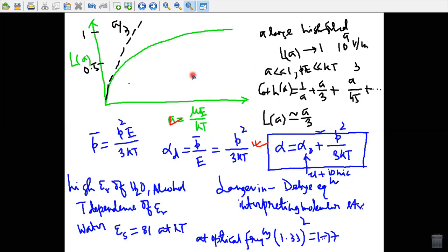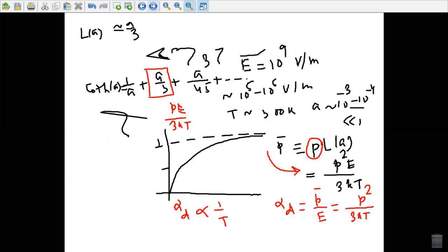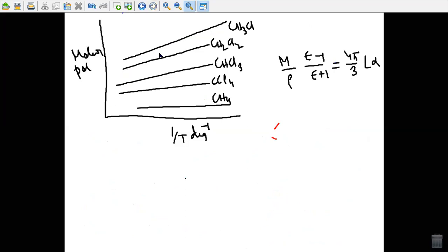As I mentioned, the polarizability arising from the orientation in the electric field of molecules possessing a permanent electric dipole moment is usually discussed only with reference to gases and liquids, but it is of importance in other solids. This type of polarization was first discovered by Debye, who showed that by assuming the molecules could have permanent dipole moments, one could explain the high dielectric constant of water, alcohol, and other similar liquids, and the temperature dependence of their dielectric constants.